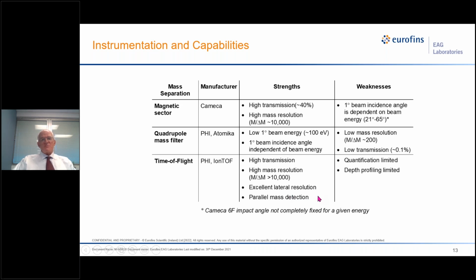It sounds like, oh, that's the perfect SIMS instrument. But quantitation is somewhat difficult, and depth profiling is limited because the pulse nature of the primary beam does not really erode very much of the sample. You have to have a separate ion gun to erode the sample that is different from the ion gun that creates the signal.